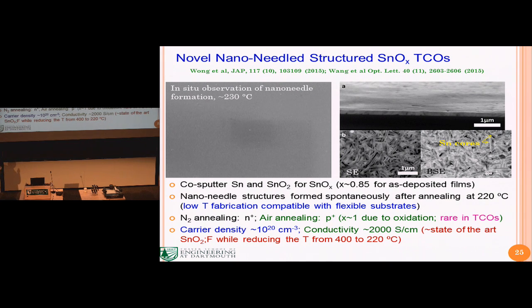And actually, they form in a very short time. As you see, in half a minute or so, it's already showing some features, and later this will grow very quickly. Within a minute or so, you'll form this kind of nanoneedle structure.